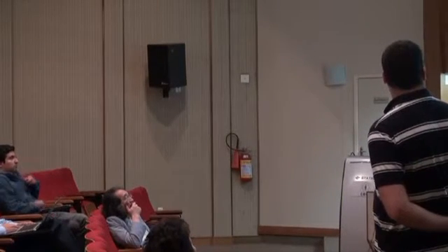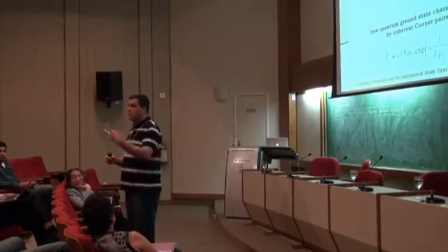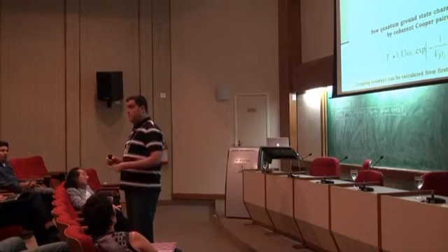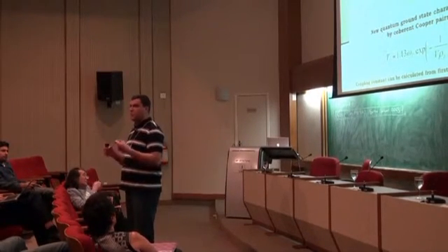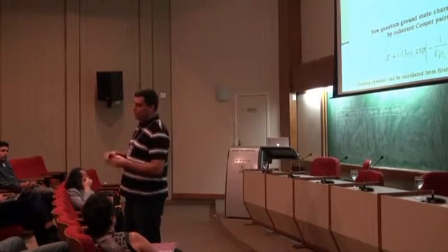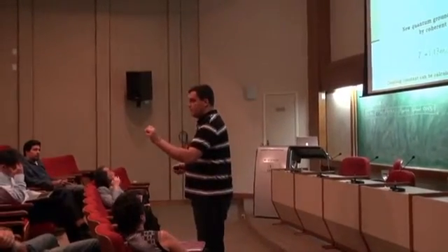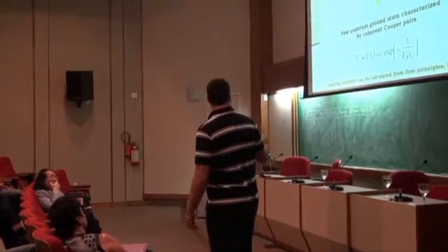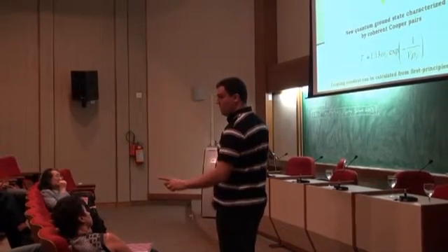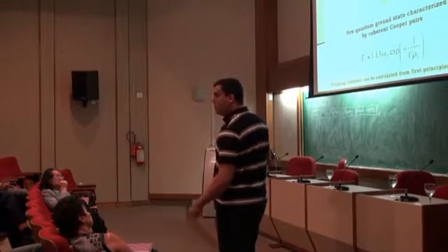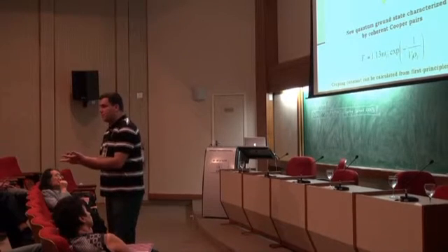It is actually, believe it or not, lithium under pressure. It superconducts without pressure, but under pressure it has the highest Tc. Why? Because of something that I will try to show with this expression here. What happens if you apply pressure? You start changing the lattice. The lattice is what gives the attractive interaction between electrons. If I'm near a lattice instability, where the lattice is going from one symmetry to another, say cubic to tetragonal, there are two main effects. This frequency here changes and usually decreases, but the coupling constant, this V, increases because the lattice becomes very soft.